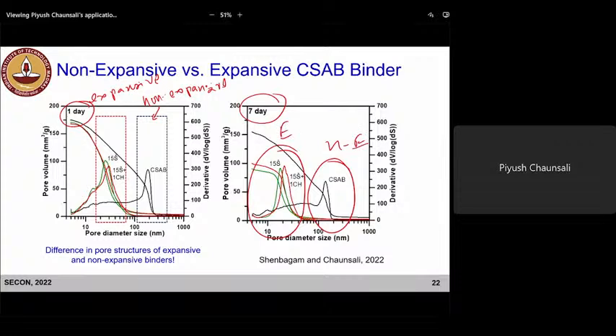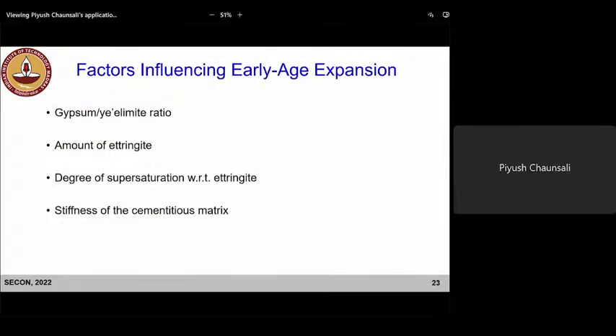So what is causing this shift in critical pore size? We'll see that the expansion is influenced by the M value, which is the gypsum to ye'elimite molar ratio, and the amount of ettringite. The more ettringite you form, the higher the expansion will be. Also the supersaturation with respect to ettringite: what is the environment, what is the supersaturation? And also the matrix stiffness, whether the stiffness is high or low, because these are crystals in a matrix. If the matrix is not very stiff or not resisting this expansion, then we'll see a high overall expansion. So all these factors affect the expansion.